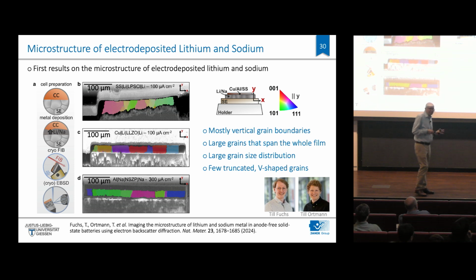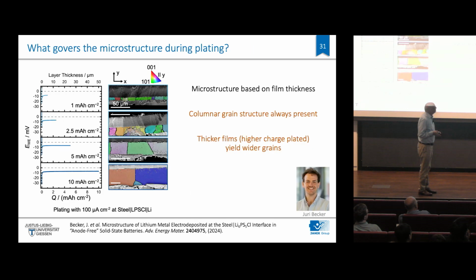50 micron lithium already means 10 milliamp hours per square centimeter, and for the battery specialist, that is more than you need. Typically, for a competitive lithium-ion battery, you would need to cycle maybe 20, 25 micron lithium. So this is already more than would be needed, and it's just one grain. And the question is why, and how only one grain? Is it current density that is decisive?